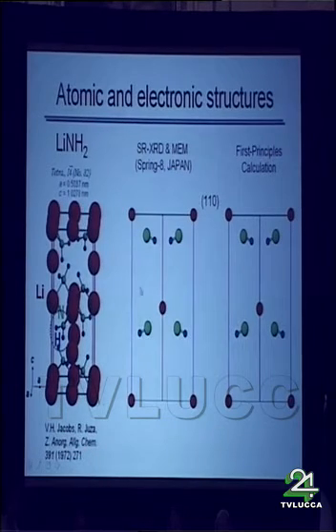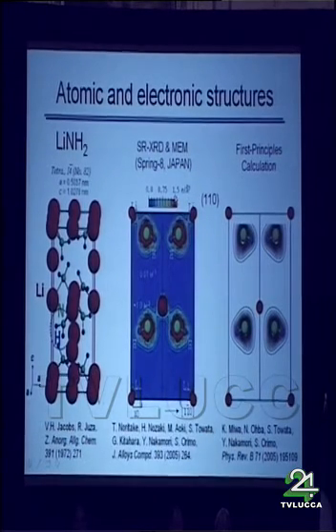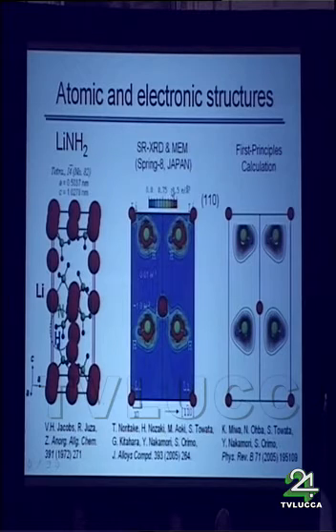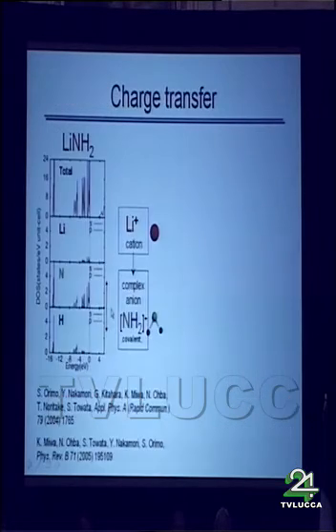So here is the location of atoms of the 1,1,0 plane, and then we have determined the electronic distribution of the 1,1,0 plane like this. Experimentally and also theoretically, apparently lithium is donating electron to the, let's say, NH2 cluster, and the electron is highly localized around the clusters. Also, the partial density of states of lithium, nitrogen and hydrogen indicates the charge transfer from lithium cation to the NH2 anion